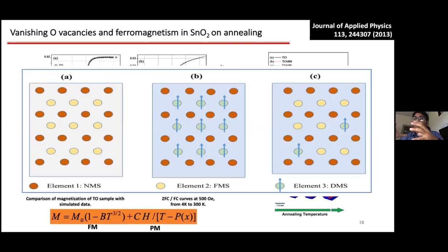That means this electron spin is associated with some lattice vibration, or polarons, basically some kind of effective charge due to lattice distortions, and those couple to each other if they are in such a large density, and then they can give rise to long range ferromagnetic order. However, if they are not in such large densities, they can actually remain isolated.